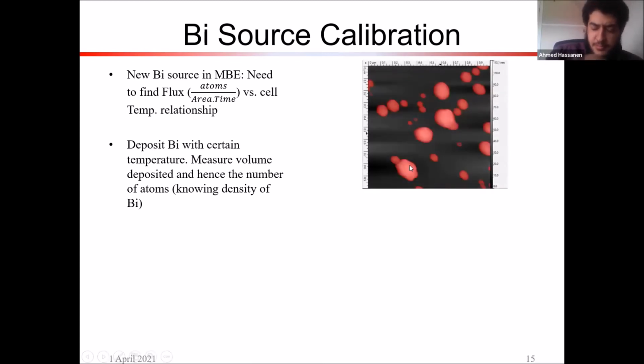These are bismuth, this AFM image of the bismuth deposited on the silicon. And so using some image analysis, calculating the volume of these droplets and knowing the density of bismuth, we can now know the atoms of bismuth, how many there are. And so knowing this relationship between the temperature and the atoms,